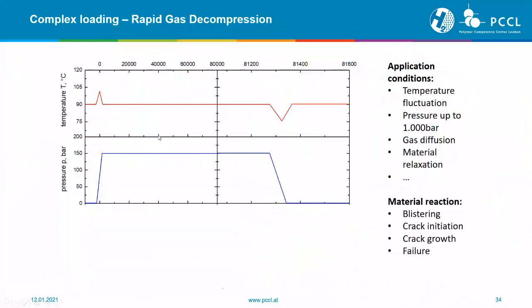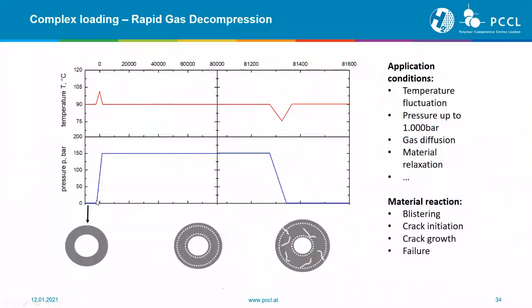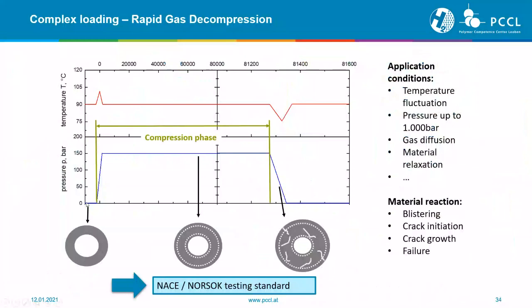What we can see here is that at the beginning we always have a compression phase, which means that we apply temperature and pressure, in this case up to 150 bars. This means an increase in the volume of the material due to the penetration of the gas inside the material. Then when we disturb this equilibrium state, our decompression phase starts, where we have some temperature fluctuations at the beginning and at the end. With this decompression phase, the stored gas inside of the material leads to an even higher volume change, and then finally to a cracking of the material. So in this case: blistering, crack initiation, crack growth, and then finally the failure.